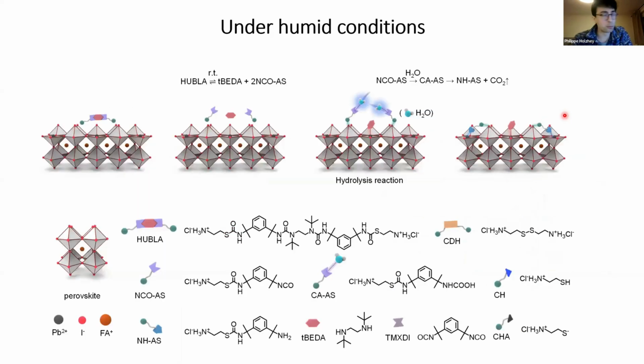And now we have a few more schematics, which show this in detail. So at room temperature, we have the HUBLA, and this is switching on and off between those two different states. And then we have the water coming in, and it can react with the NCOs to then form NH2s and CO2. And depending on where it's sitting, it can react with different forms of defects and bind to them and passivate them. So it needs water for the dynamic covalent bonding with that.